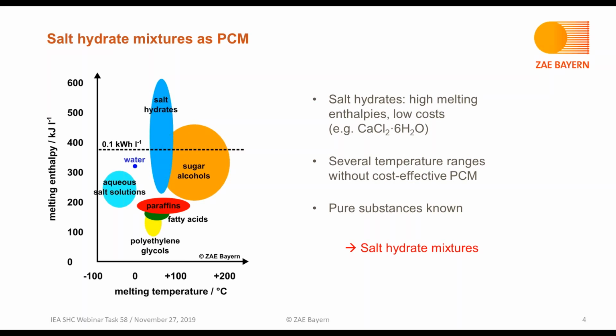An example of a salt hydrate would be calcium chloride hexahydrate. So the salt is calcium chloride, and 6 moles of water are coordinated around the salt. However, there are today several temperature ranges without cost-effective PCM, and as pure substances are mostly known, we are developing salt hydrate mixtures to create new PCM.